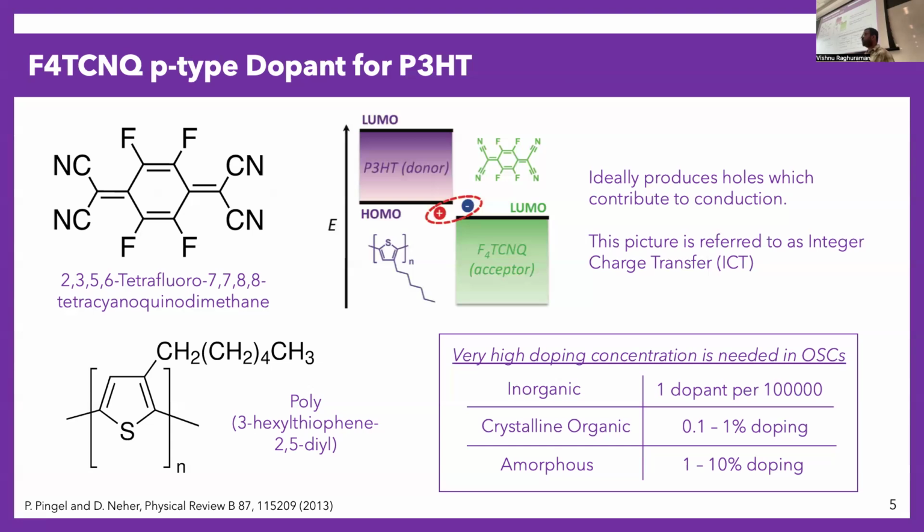So if you have 10% doping, that has serious morphological implications because the doping will now affect the actual crystal structure or the RDF of your system. So all those very neat theoretical diagrams that you may have seen for silicon, where you just take out a silicon atom and put a phosphorus atom there, and you'd add one energy level to your band gap, and you assume the rest of your morphology doesn't change as much. Those types of things don't apply anymore. So your morphology and your doping are very coupled problems.